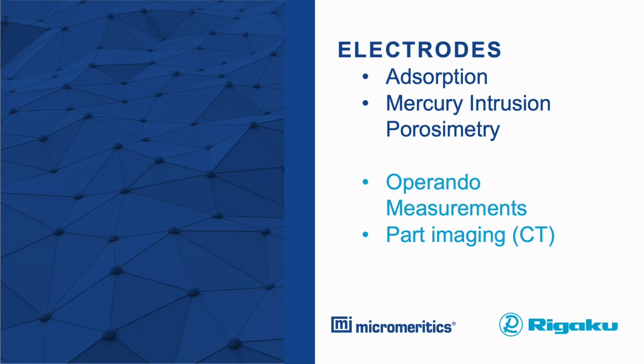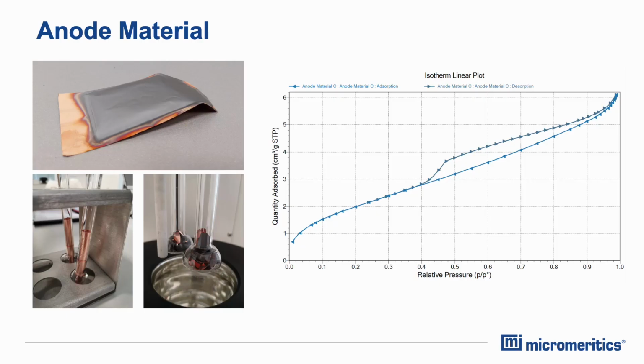Thank you, Stephan. I will start by continuing with adsorption. Looking at this example, we see that this is an anode material, and for this anode material we measured the whole isotherm, including the adsorption and desorption branch. From the isotherm data we can now calculate the BET surface area and the pore size distribution, and already the shape of the isotherm tells us this electrode contains mesopores, what we see from the typical shape with the hysteresis closing at a relative pressure of 0.4.